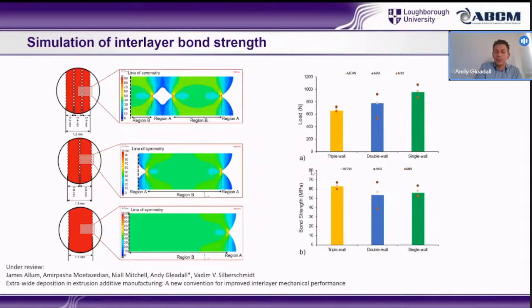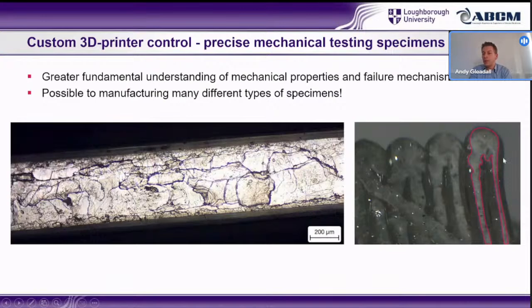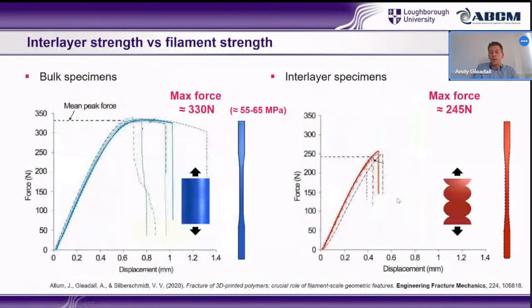It also allows us to do nice finite element analysis to support our experimental understandings. That's what we're seeing on the right, how the experimental results, which are the bars, really fit in nicely with what we'd expect from the simulation data. Whereas again, doing a finite element analysis of this contact area would not really be a sensible thing if it's not repeatable. So we did our testing, and we were quite aware of these grooves in the side potentially having stress concentrating effects. And these are the results for testing along the direction of filaments.